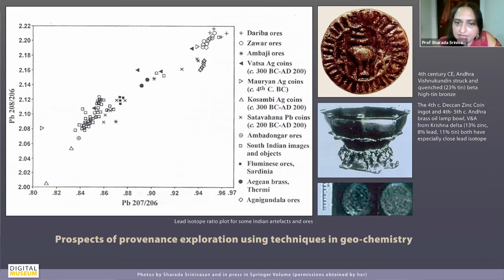But the lead isotope ratios of this did not match Zawar. So it seems to be another ore source. But because I'd also done compositional and trace element analysis, and the fingerprinting also involved a combination of lead isotope ratios and trace element analysis, I've given talks about that later. It does seem to very well fit another Andhra brass oil lamp, the lead isotope ratios and so on, which was also a brass lamp that you're looking at here from the Victoria and Albert Museum, with 13% zinc, 8% lead, and 11% tin. So it was a source that was known to southern India. And the trace elements also matched the Vishnukundan coin because of the copper source being the same. So the southern Indian provenance seems to be quite likely here.